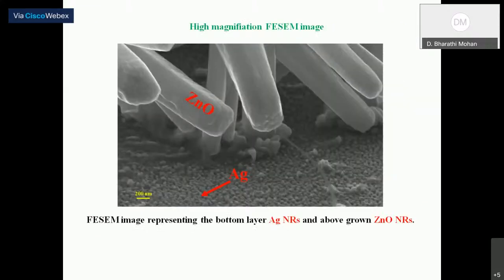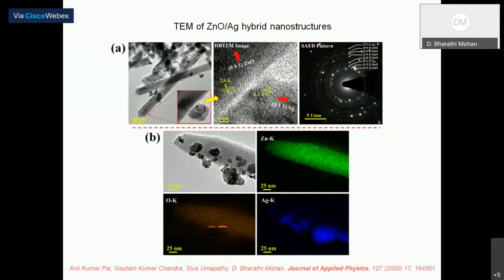So this picture gives clear information about the bottom layer as well as the zinc oxide that is grown on the silver film. So from the TEM image, we understood the formation of the hybrid structure of silver and zinc oxide phase, and the crystal structure from the HRTEM image has been understood, and further it confirms the presence of silver on the surface of the zinc oxide phase.